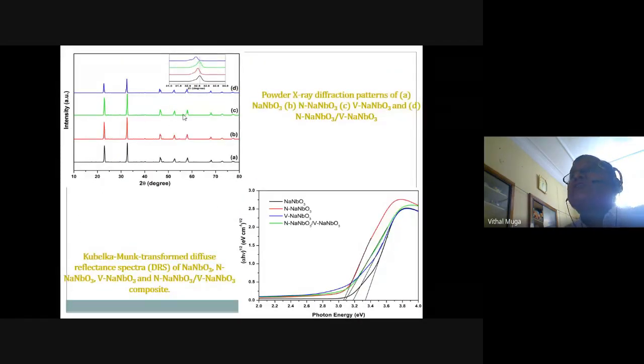Now you see that this is the powder XRD. Everything is actually the same. The structure has not changed by substitution of nitrogen or vanadium. But if you look around this peak, there is a systematic shift. Now this is sufficient for us to confirm that nitrogen and vanadium have gone into the lattice. Now you see the DRS spectrum. Now if you look at the DRS spectrum, the NaNbO3 and N doped, V doped, and the composite, then you look at the change in the band gap energy. Band gap energy changed considerably.